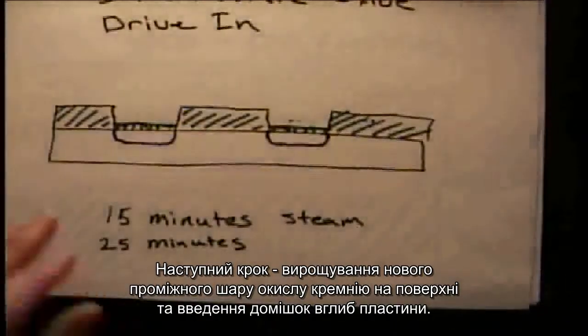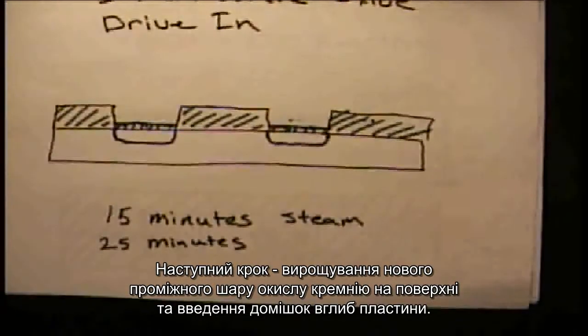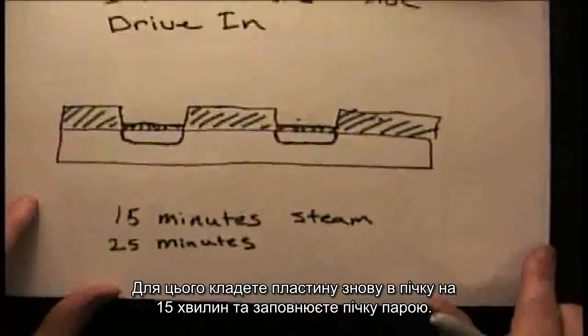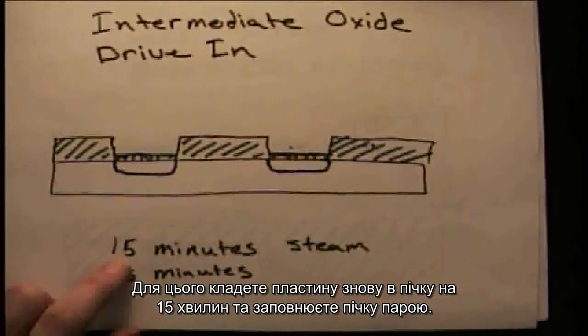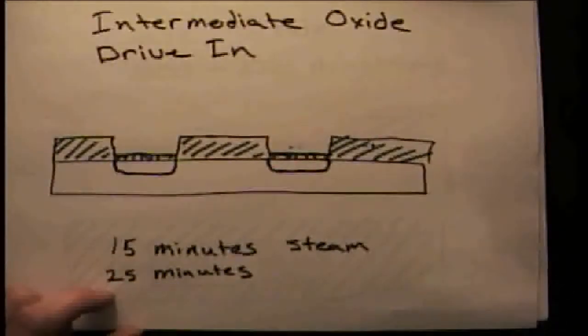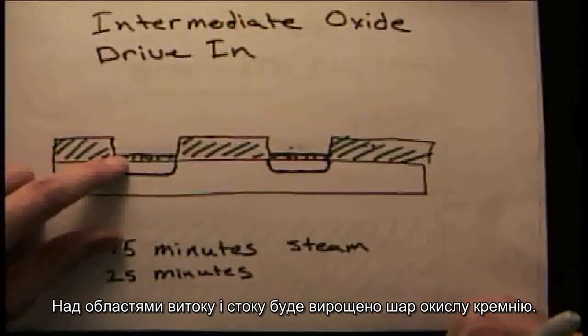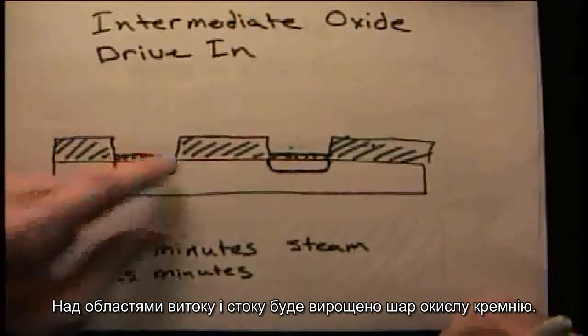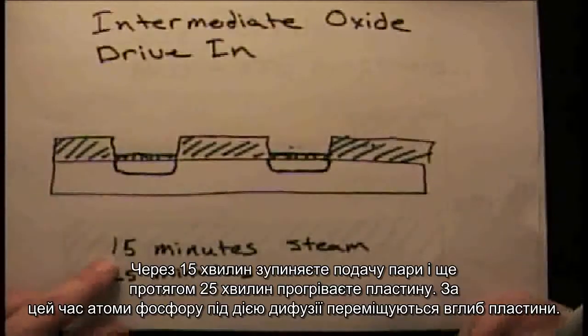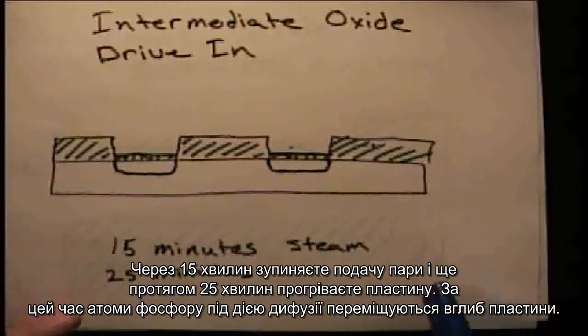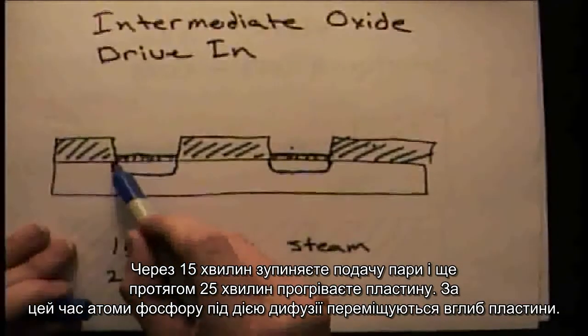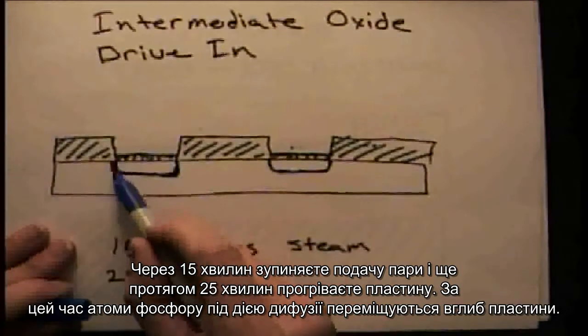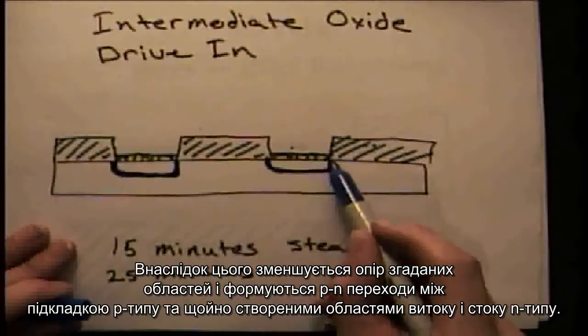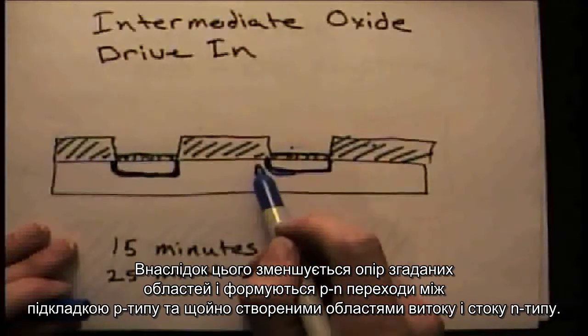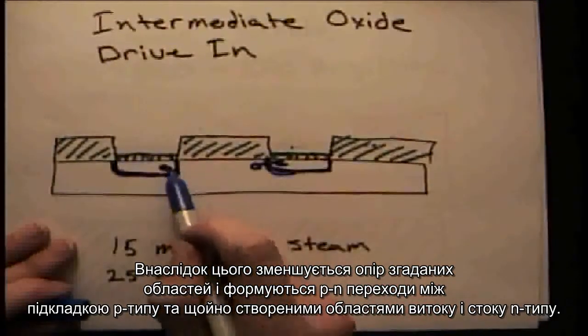The next step you're going to do is the intermediate oxide layer and the drive-in. So you're going to put it back into the furnace. 15 minutes of pumping steam into the furnace. It'll grow an oxide layer to cover up the source and drain regions. And then you're going to stop the steam, and for 25 minutes you're going to drive the phosphorus into the wafer. This will lower the resistance in this area and form PN junctions between here and here, and here and here.